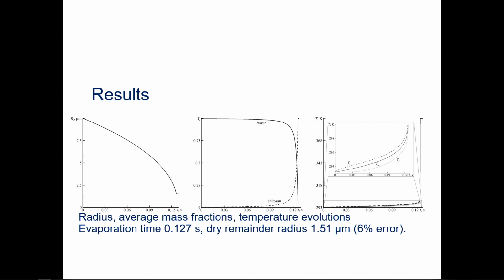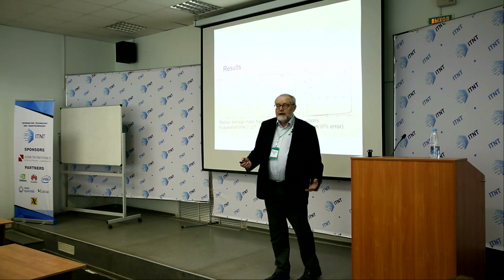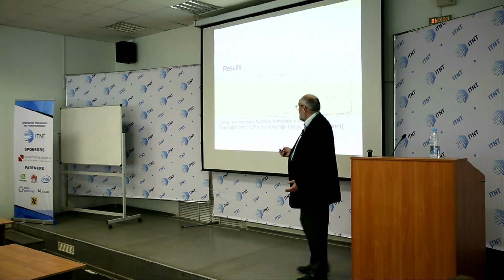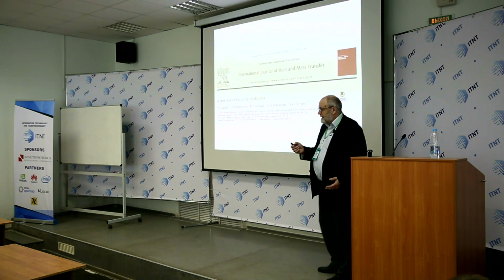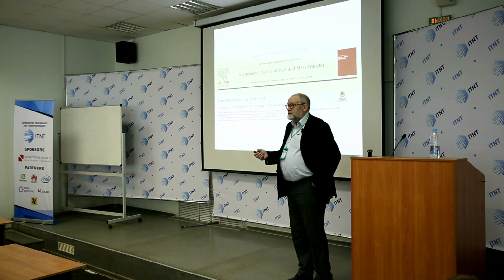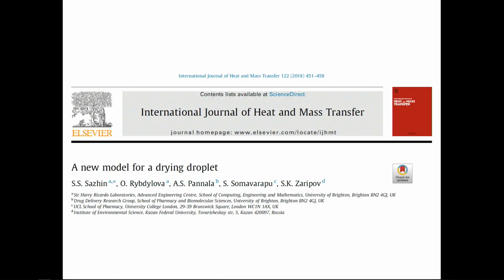And we cannot really validate rigorously all these plots which are shown here. But what we can validate is the typical time of evaporation of the droplets. And the typical time of the evaporation of the droplets, about 0.12 seconds, is compatible with the experimental observations. And these results were published last year in our paper, prepared together with a colleague from the Department of Pharmacy at our university, and also colleagues from Kazan University in Russia, not far from here.